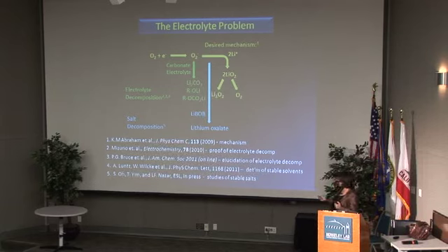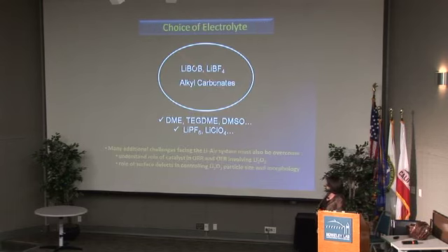Mizuno really clearly showed this electrolyte decomposition. Peter Bruce has elucidated how it decomposes, and this group at IBM has determined what the stable solvents are. We have been looking at some of the salts, and we've discovered, as I said, that this tears up almost anything. So even things like LiBOB and LiBF4 are chewed up by the peroxide, in this case, for example, to form lithium oxalate. So we have a big problem. The first intermediate is a real issue. So we don't use alkyl carbonates or LiBOB or LiBF4.